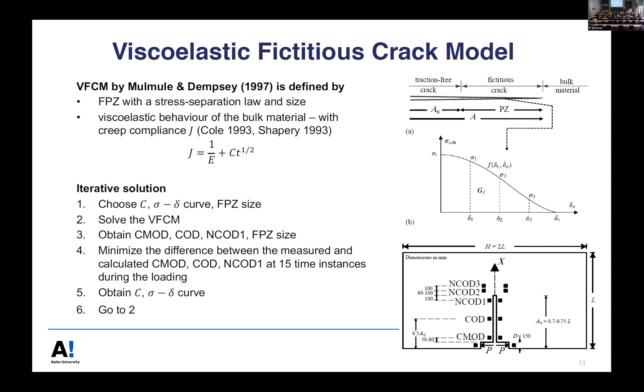[Questioner]: There are models using a damage function from 0 to 1, which opens the way to phase field models for cracks. Did you try those? [Speaker]: We only used these two models — linear elasticity and the viscoelastic fictitious crack model. What you describe has been used with ice in a damage mechanics sense, but that involves a cloud of cracks. Here we're looking at a single crack tip. In this process zone one could think of it as damage mechanics, but this was not our approach at this stage.